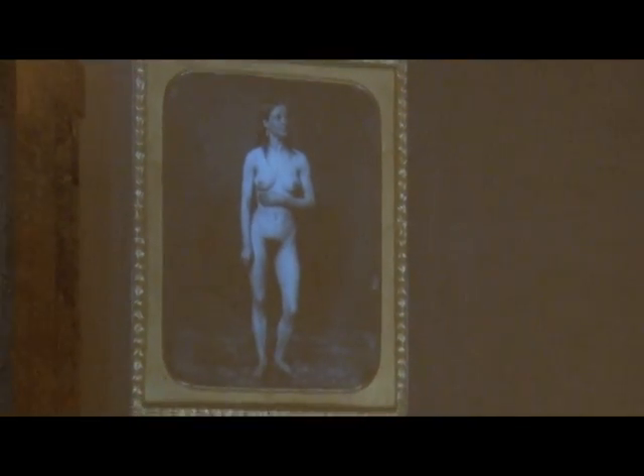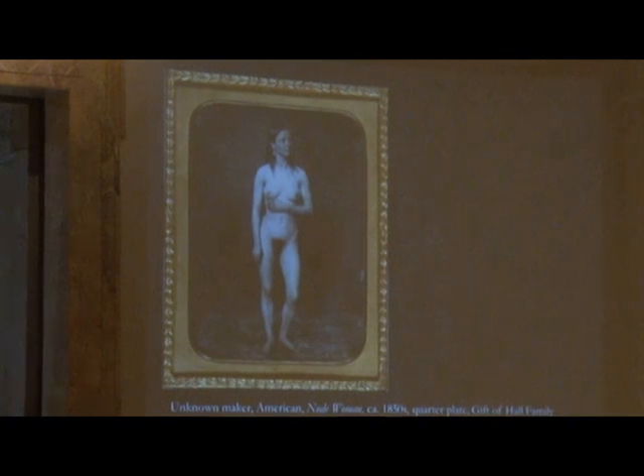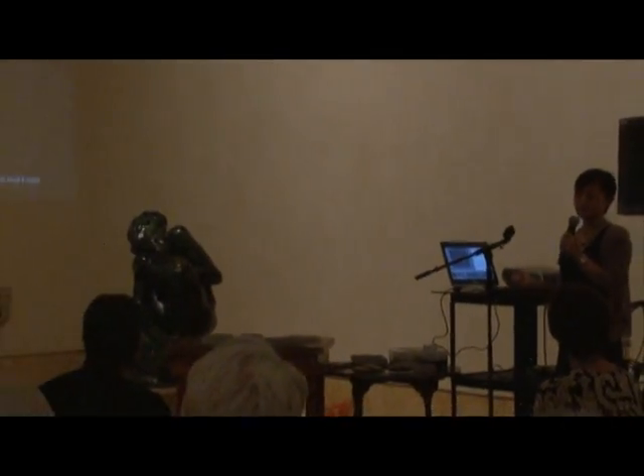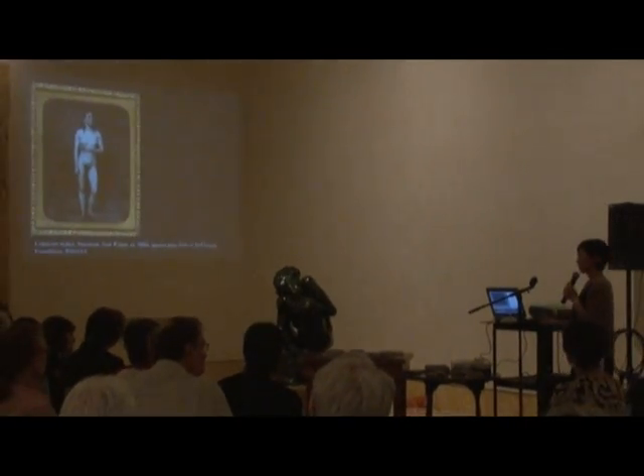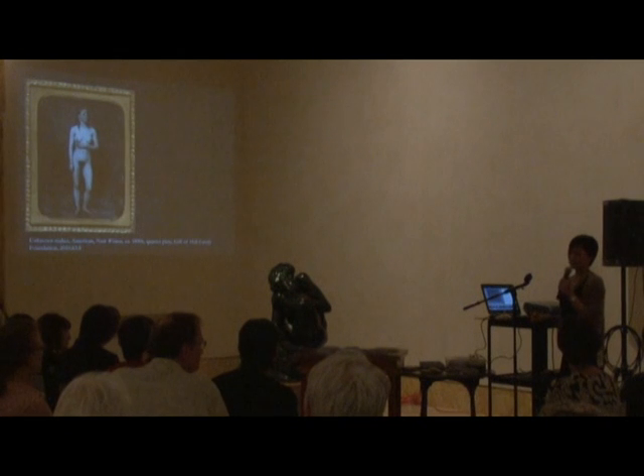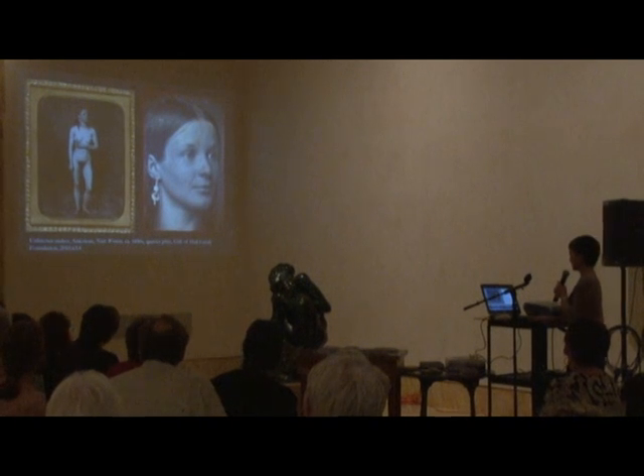Other than corrosion caused by glass debris and poor environment, inappropriate treatment can cause tarnish on plate. This plate had been cleaned using a chemical called thiourea in the mid-1990s by the owner at the time. And this chemical was commonly used to remove tarnish of daguerreotypes in the late 1950s. It was really popular because it was really easy to administer, and the result was really instant. But over time, photography conservators started noticing these yellow spots forming on the plates that were treated that way.